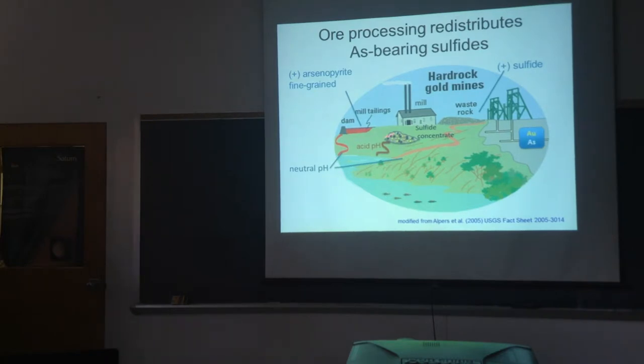to cyanidation. And these can lead to acid conditions because you have a lot of pyrite, let's say, and nothing to neutralize it. In the mill tailings and the waste rock in the mud, you tend to have carbonate minerals such as calcite, dolomite, and even siderite that can play some role in neutralizing the acids that are generated when the pyrite oxidizes. But if you have a sulfide concentrate without much carbonate, this will generate acid runoff. Whereas the runoff from most mill tailings associated with gold mining are actually neutral.